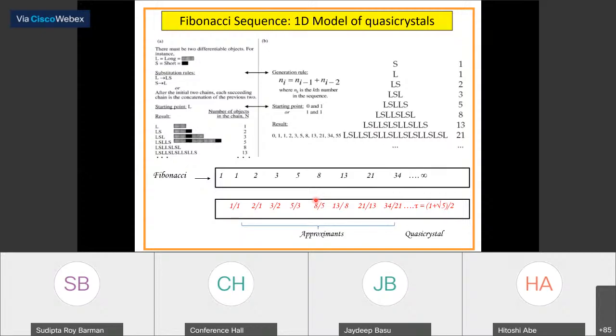So to understand what approximants are and their relation to quasicrystals, this is the Fibonacci series that is well known, for one-dimensional quasicrystals, where you can see that if this series goes to infinity, then between long and short and so on, then it is a quasicrystal. On the other hand, if that is terminated, for example, we'll talk about 2x1 approximant, 3x2 approximants. So that would mean that we have three long and two short, and that is repeating. 8x5 approximant will mean that we have eight long and five shorts, and then that is repeating. So as these numbers grow, that would mean that we are getting to bigger and bigger approximants. And if this goes to infinity, then we reach the ratio between these two numbers to tau, which is called the golden mean. And that is a perfect one-dimensional quasicrystal.